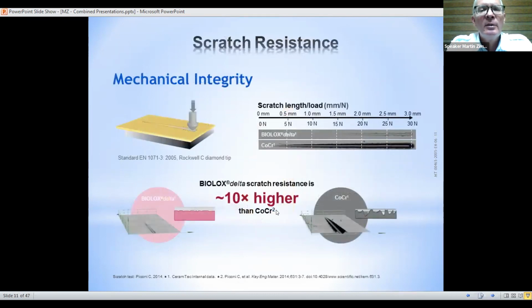So the reason why ceramic behaves better than cobalt chrome, I think it's well known to everyone, is due to what we call the scratch resistance. And this is easily measured by making an indentation at the surface of the material. We can demonstrate that the ceramic material, Biolox Delta particularly, is 10 times more scratch resistant than cobalt chrome.